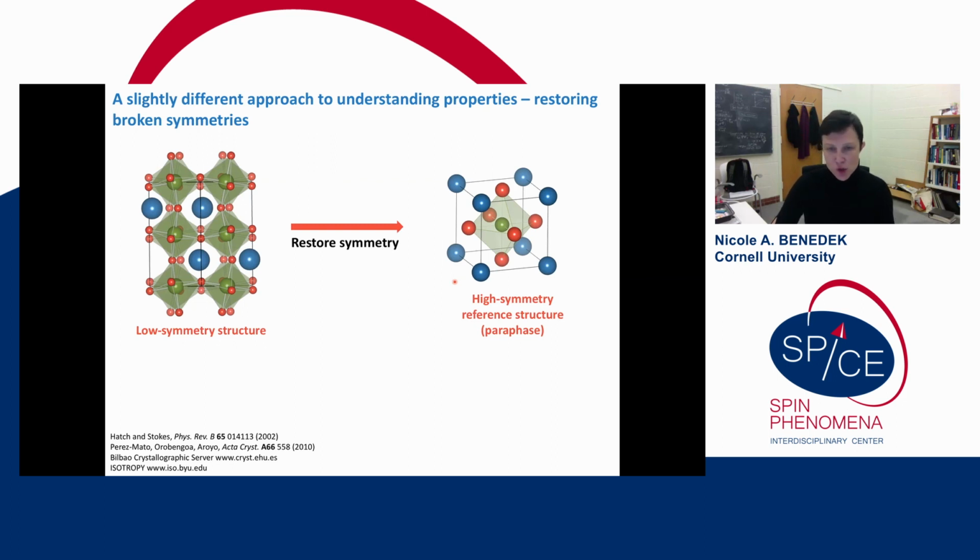The structural distortions that relate these two structures are known as modes. We can often associate them with phonon modes of the high symmetry paraphase. They transform like some irreducible representations of the paraphase. And we can treat those modes as kinds of order parameters in a Landau theory.